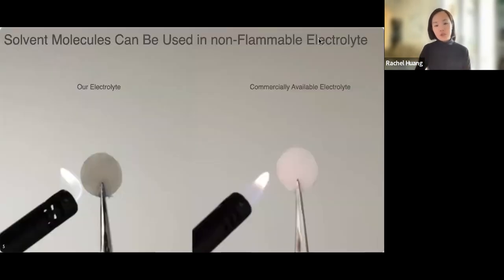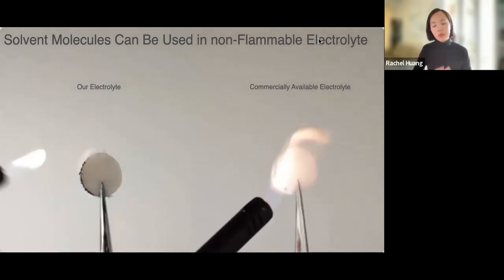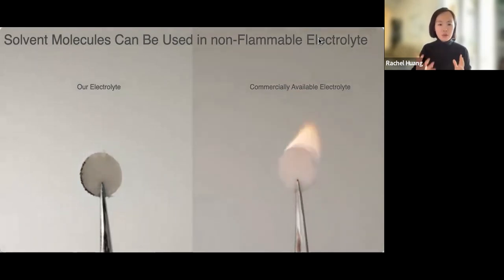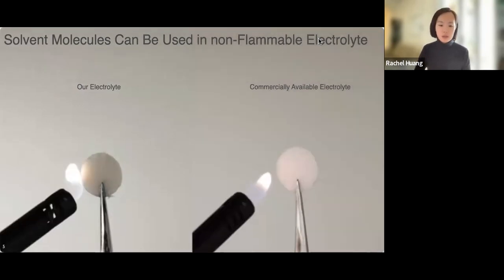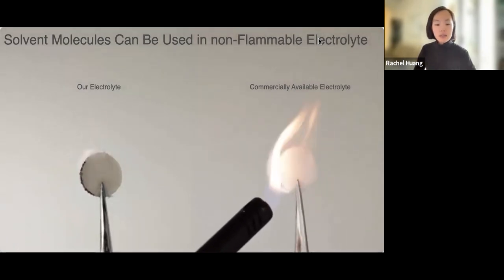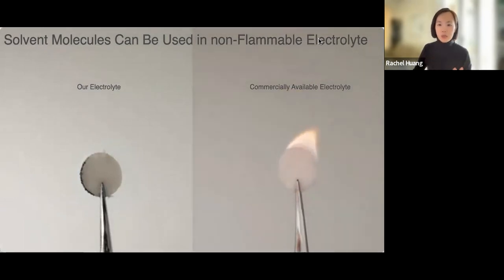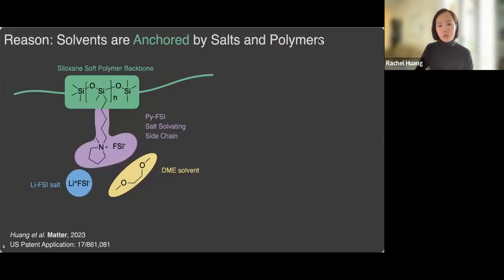In this video, we soaked a glass wool with our electrolyte and with a commercially available electrolyte that is in our phones and tablets. We soak it in a glass wool so the glass wool itself won't burn. For our electrolyte, when it is approached with the flame, only charring happens. But for commercially available electrolytes, the flame was sustained until all the solvent molecules were exhausted in the system. So what is the secret? The secret is that those solvent molecules are actually anchored by salt and polymer in the system.